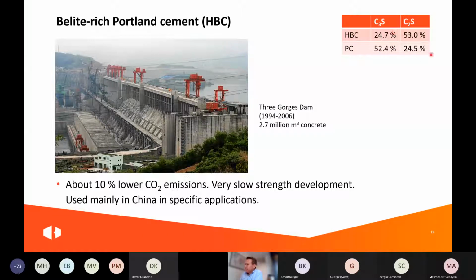And this is a comparison with Portland cement. A bit of a strange Portland cement. Normally this amount is higher than what's here the reference. But the reduction is only 10% in CO2 emissions, and we have a very slow strength development. So it's only suitable for very specific applications like this dam where it was used. There you have the advantage of a very low heat development.